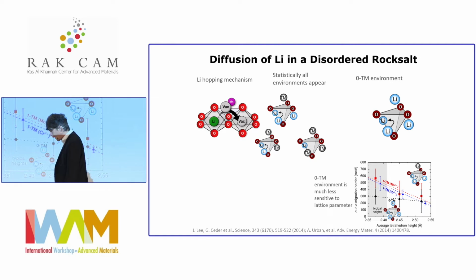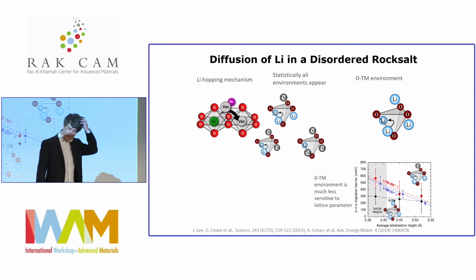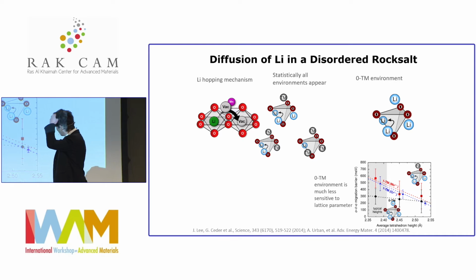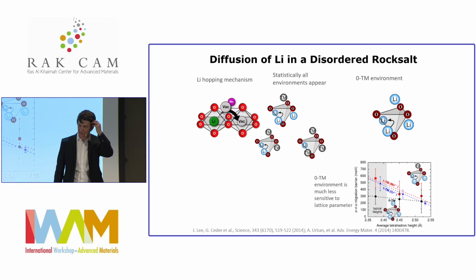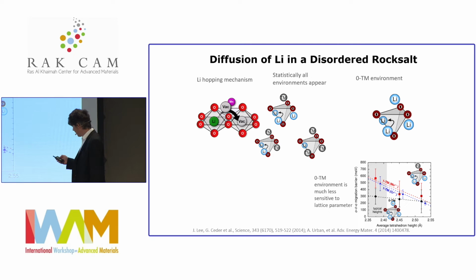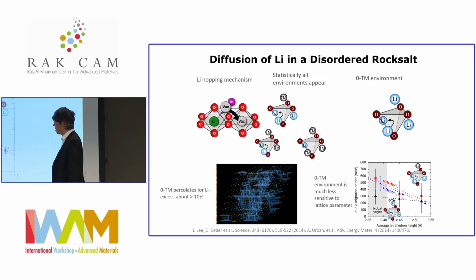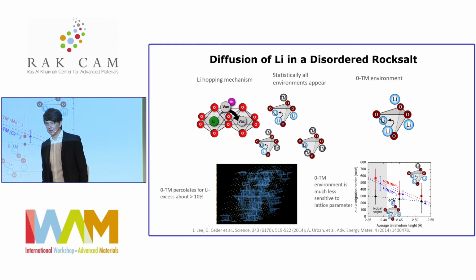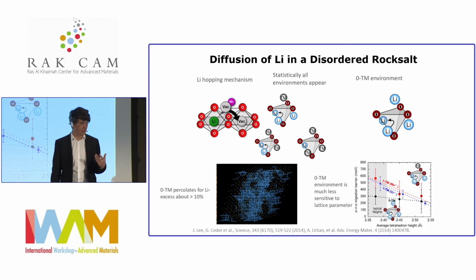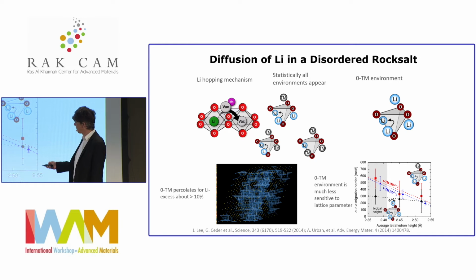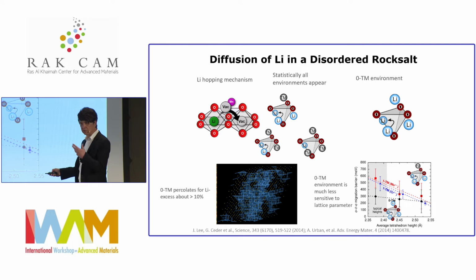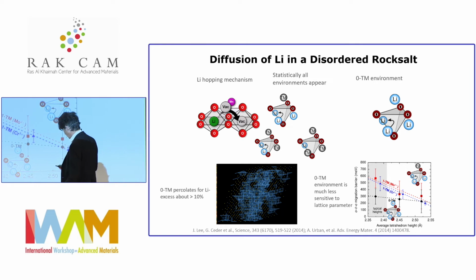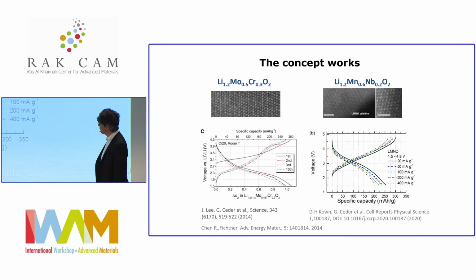And this is where the tiny little bit of physics that I learned in graduate school, when I also occasionally took a course in physics, came in. I had learned about percolation theory, and so I realized that this is really a percolation problem. You just need enough of these so that you have macroscopic diffusion. And percolation theory gives you an exact answer: if you randomly distribute it, you just need 10% lithium excess, and you will have a percolation network that statistically percolates all the way through the crystal structure. And that was proven in 2014 by us and then by Fichtner and Chen in Germany.